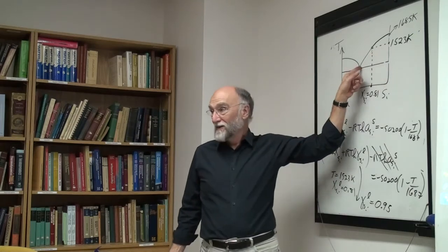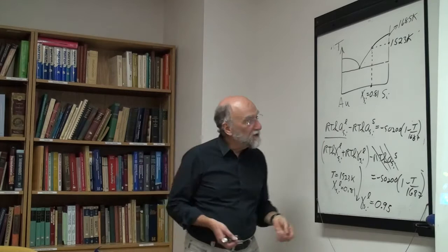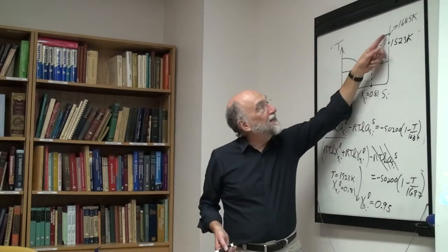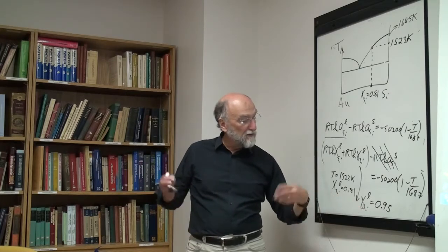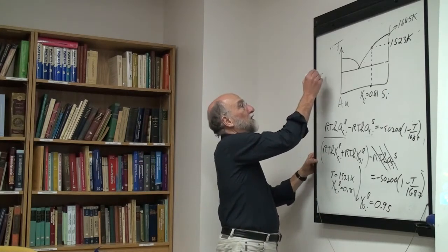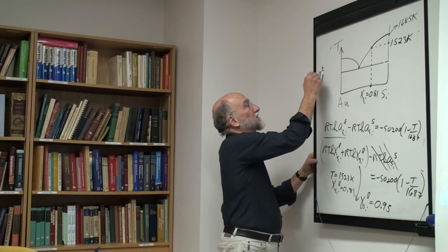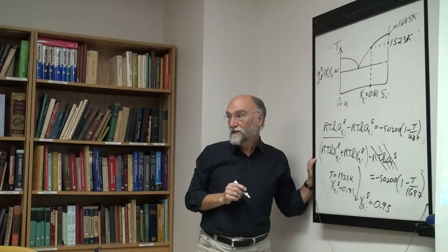this liquidus. But when I do a model, what I will do, when you're using an optimization, is you don't just calculate gamma point by point. What you do is you come up with some sort of a model. RT ln gamma is a regular solution model or something. Let me show you what I mean. So you have the regular solution model. So let's assume the GXS of the liquid is X1 X2 times omega.